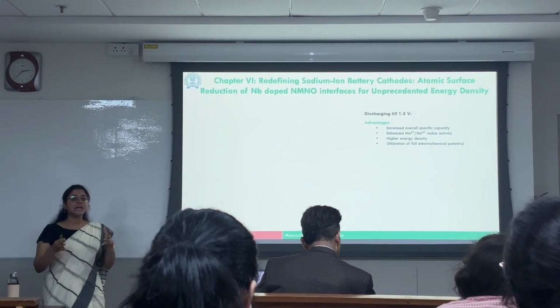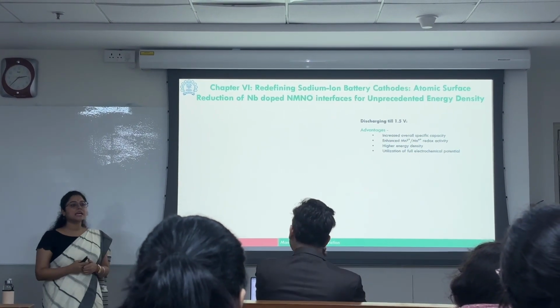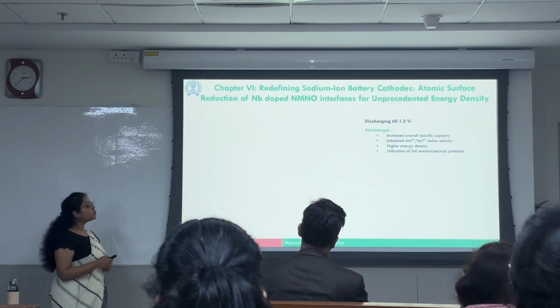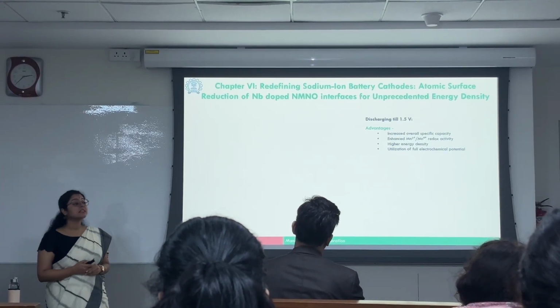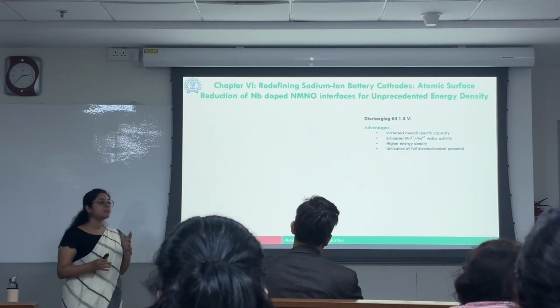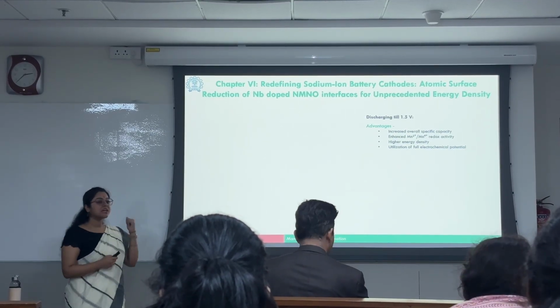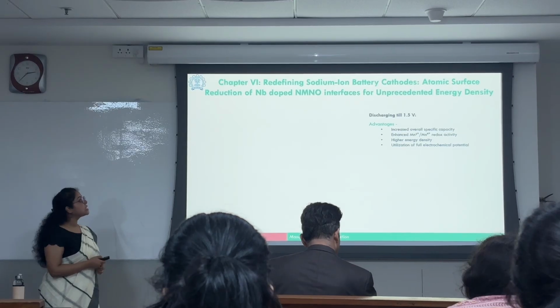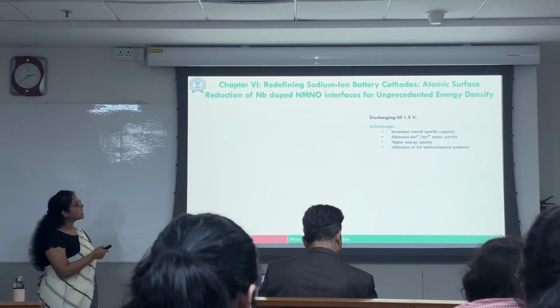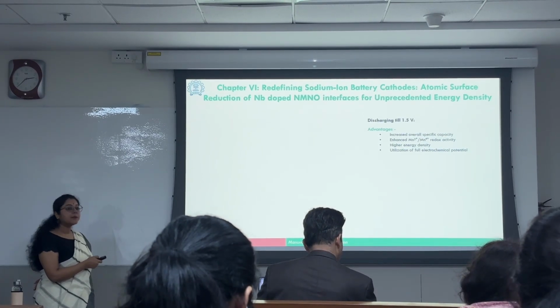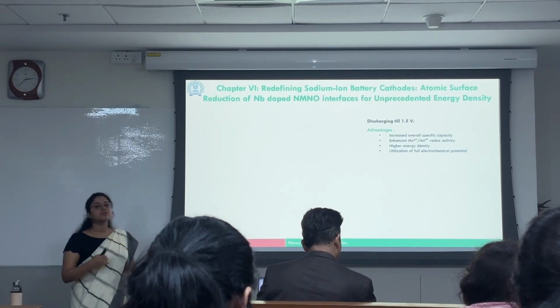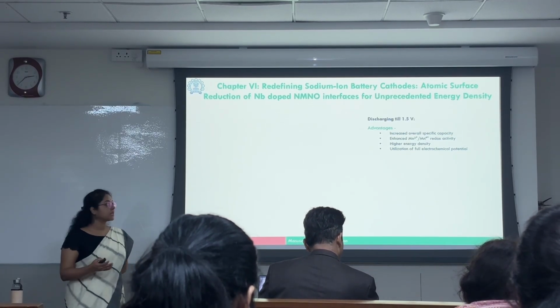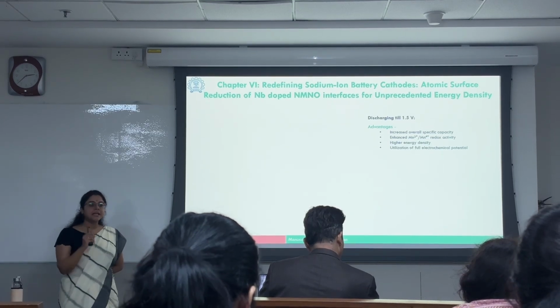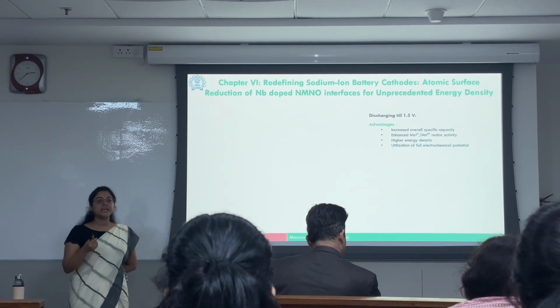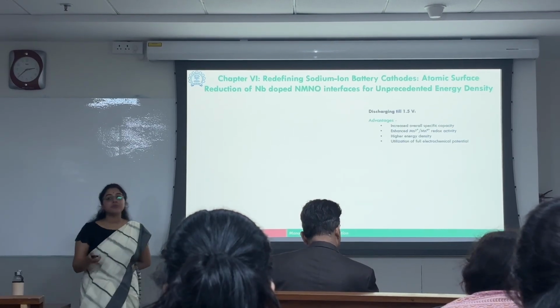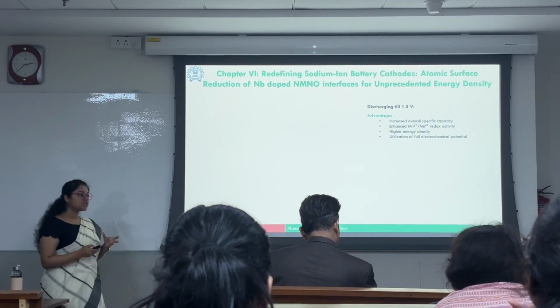So as of now, we have seen that we were discharging the cathode material till 2.5 volt. We had seen through the DFT analysis that the niobium doped NMNO was much more stable over a wider potential window, as we had already seen in the previous slides. That is why we chose that particular cathode material and discharged it till 1.3 volt in order to get the advantages of increased overall capacity, incorporating the manganese redox activity, and also get higher energy density out of it, and finally utilize the full electrochemical potential window.